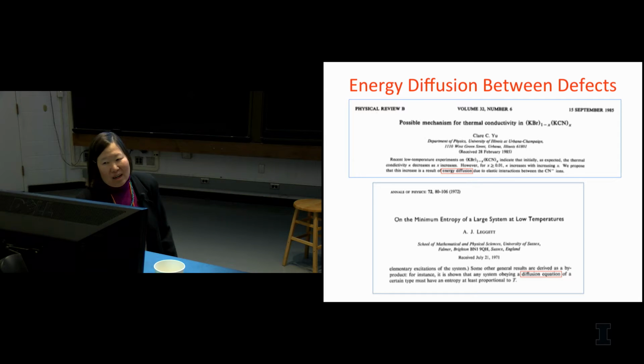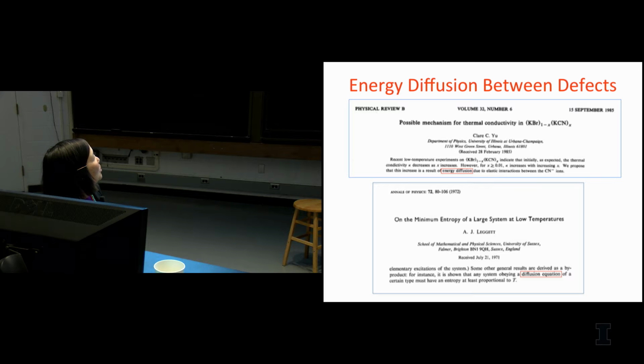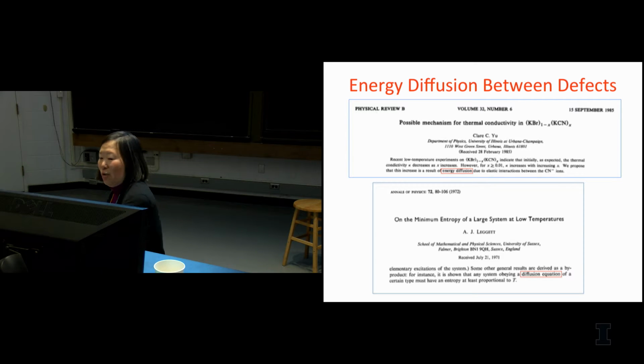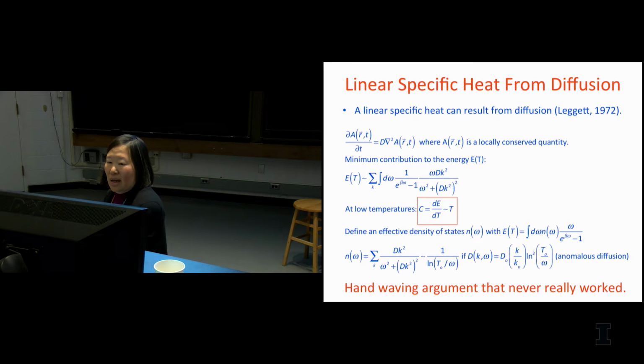But I showed this paper to Tony, and I think it perhaps jogged his memory about some work he had done quite a bit before that on the entropy of systems, in which he pointed out that if you have a diffusion equation describing something in this system, you could have an entropy that went linear in temperature and therefore a linear specific heat. So he said maybe this would apply to glasses, and the idea here is that you have a locally conserved quantity A, obeying a diffusion equation. You write the energy in terms of some diffusion kernel, and then that gives you a linear specific heat.